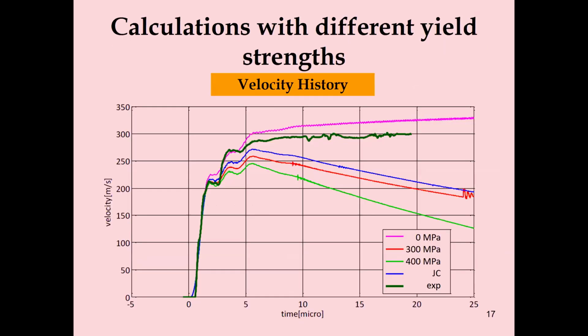So if we look at the velocity history, what we could see here, the green thick line is the experiment, and all the others are simulations with different strength. So first of all, if we look at the velocity history, we could see that it's oscillating, and each of the steps we're getting here is referring to one of those oscillations. So that's how it's pushing it in steps. But if we look at the overall behavior, we can see that later on we're getting this kind of inclination of the velocity.